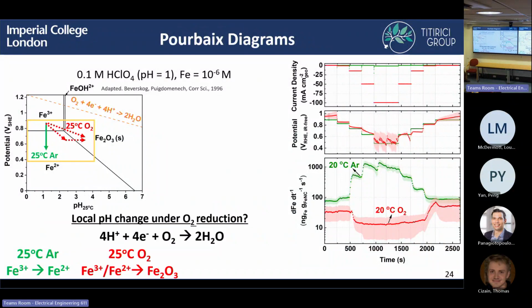So if we look at the Pourbaix diagram, we think what is happening is we go from around 0.9 volts, and as we're stepping down in potential, the current density increases, and as we increase the current density, we're consuming more protons. So the reaction of oxygen reduction, just to remind you, you have 4 protons, 4 electrons, and oxygen, and you produce 2 water. So as we consume more protons in the catalyst layer, our pH can actually be increasing in the catalyst layer. And so that's what we think is happening from the Pourbaix diagram.